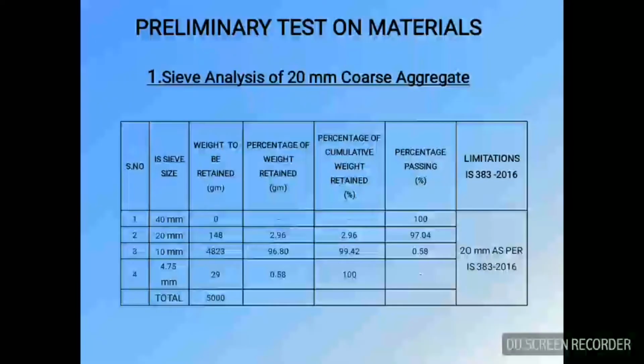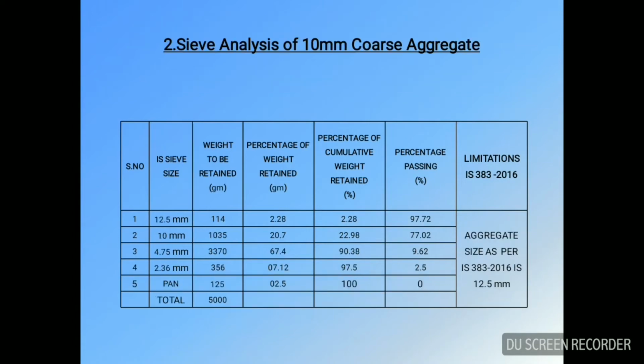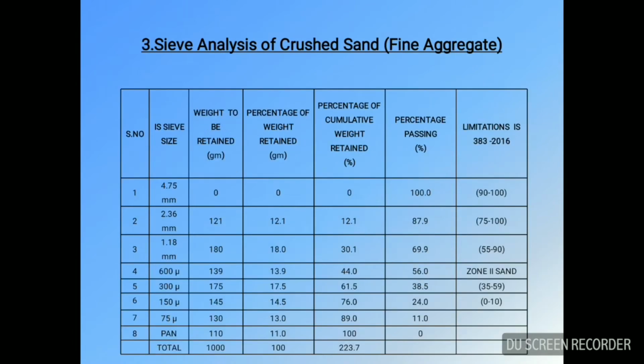First of all, for sieve analysis of 20 mm coarse aggregate, as you can see, about 97% was the passing percentage for our materials used, which was within IS limitations of IS code 383/2016. Similarly, for 10 mm coarse aggregate, this was also within the limitations of IS code 383/2016 of within 77%. At last, for sieve analysis of crushed sand, as you can see, the passing percentage of zone 2 sand was 56% for 600 micron, which was also within IS limitations 383/2016. Those materials which did not reach our limitations were rejected.